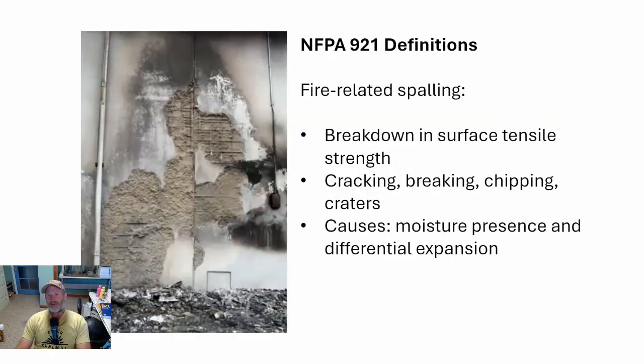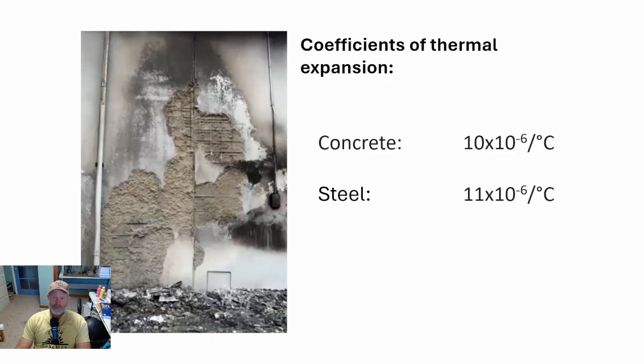Here's an example of spalling on a wall. What you see happening here is the breakdown of the surface tensile strength. It shows up in a variety of features: cracking, breaking, chipping, and craters. This is caused by the moisture presence in the concrete, as well as the thermal gradient from the surface toward the inside of the concrete that creates differential expansion rates.